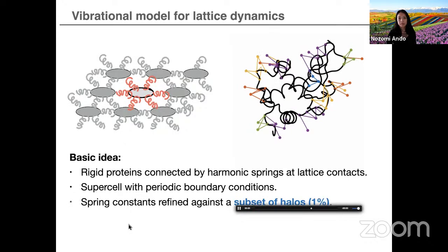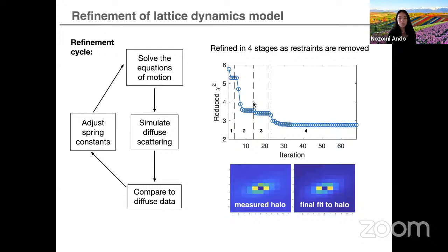This is the gist of the model. And he refined that lattice dynamics model in multiple stages, where each refinement cycle essentially entails solving the equations of motion, then simulating the diffuse scattering, comparing it to the actual data, adjusting the spring constants, and then cycling that. And then he gradually removed restraints on the springs until there was good convergence in terms of the fit and also in terms of the chi-square, but also visually agreeing with the measured shapes of the halos.